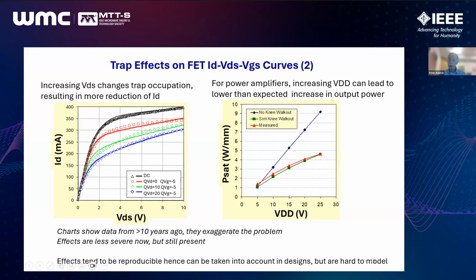As you apply higher voltage, well, one would expect that with higher VDD, the output power would increase linearly. But experimentally, this is often not the case. In fact, it increases at a lower rate than linear.